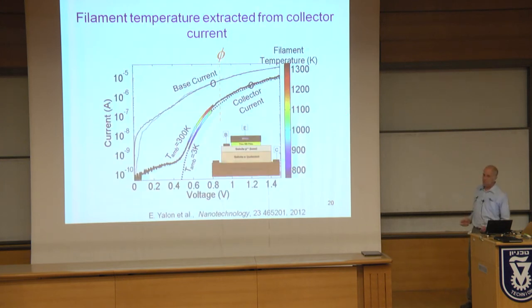This is what happened after a fairly complicated and rigorous analysis of the collector current. We can extract the temperature in the filament. You can see here the color scale gives us the temperature. The base current is actually heating the device, and the collector current, the minority carrier current, lets us analyze the device, and we can tell what the temperature is at each bias point. We can see fairly high temperatures of the filament that are extracted using this method.